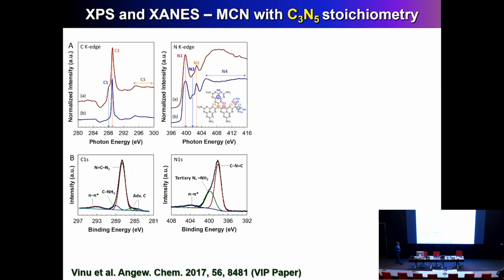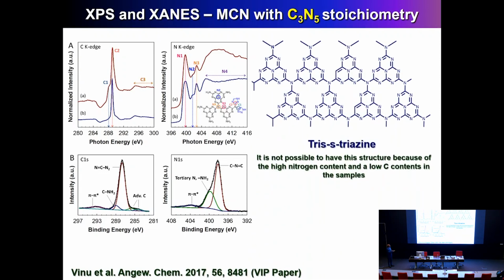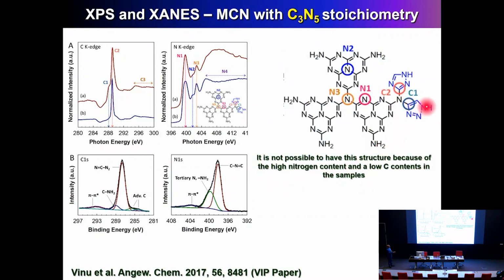So interestingly, when we analyze the nature and coordination of the carbon and nitrogen in the carbon nitride with the C₃N₅, we found that there is a huge quantity of the sp2 hybridized carbon, which is completely different from the C₃N₄. And also there is a strong pi-pi stacking. That means it's a layered material. And C₃N₄ has a tri-s-triazine structure. C₃N₅ cannot have this tri-s-triazine structure, right? Because there is no sp2 hybridized carbon, and that is mainly coming from the triazole moiety that is here.